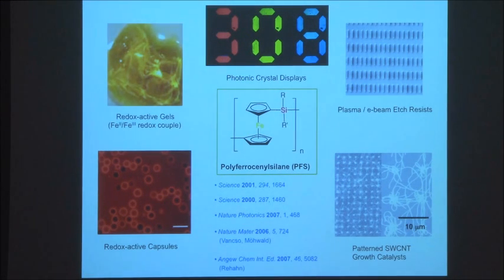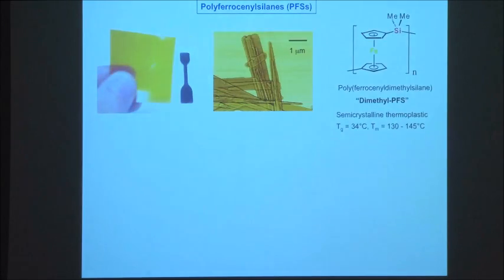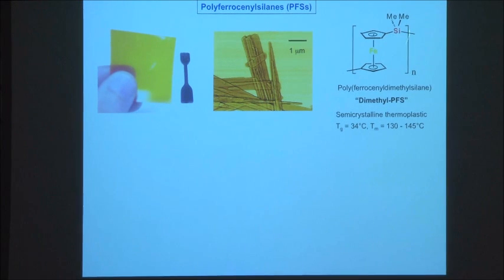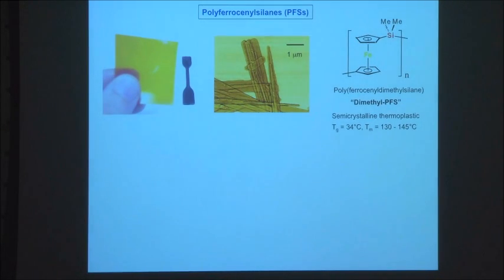So these are interesting polymers in their own right. But in terms of this lecture, the only feature of them that is significant is the fact that if you have polymers with a very symmetrical structure, so if you have two methyl groups on silicon here, the polymer chains are regular enough in their structure to actually crystallize. And in the solid state, they will pack into crystallites. In fact, you can grow single crystals of this material. I'm going to refer to this as dimethyl PFS for the rest of the lecture. You can detect a melting transition. And you can show by X-ray diffraction that these are ordered crystalline structures.